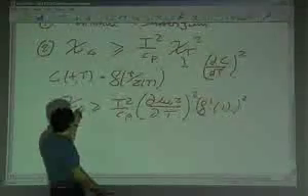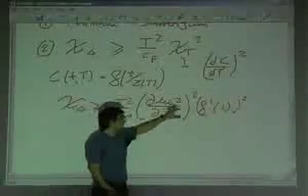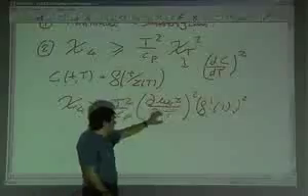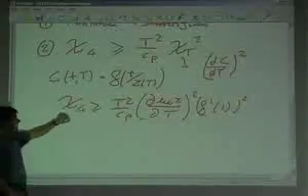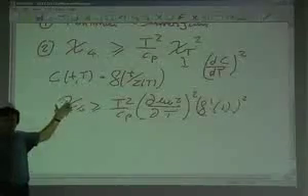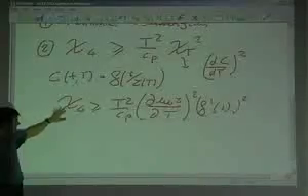So if the time scale diverges, log of tau diverges, and its derivative with respect to temperature diverges. Since chi4 is just the dynamic correlation length to some power, you again get that the dynamic correlation length should diverge if the time scale diverges, and it should increase if the time scale increases. So it is the same result, but now with the dynamic correlation length and not the point-to-set correlation length. Oh, yes?